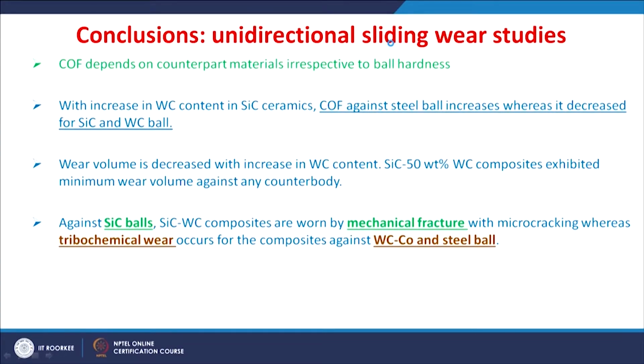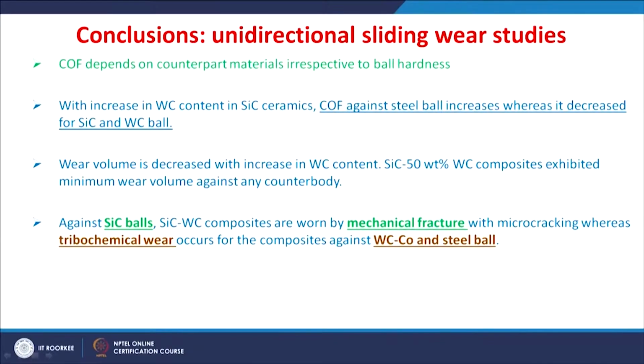So, the major results from the unidirectional sliding wear study are like this. The coefficient of friction depends on the counterpart materials irrespective of their ball hardness. With increase in tungsten carbide content in silicon carbide ceramics, the coefficient of friction against steel ball increases, whereas it decreased for other silicon carbide or tungsten carbide cobalt ball. Wear volume decreased with increase in tungsten carbide content, and the SiC-50 wt% WC composite exhibited minimum wear against any counterbody.